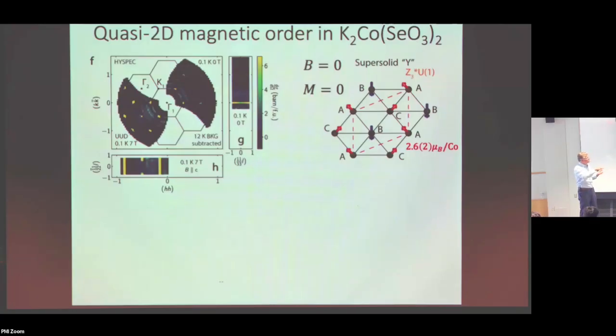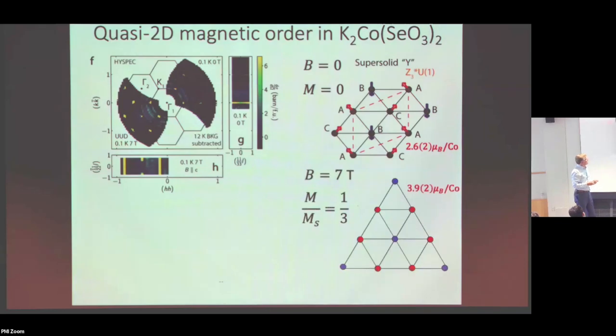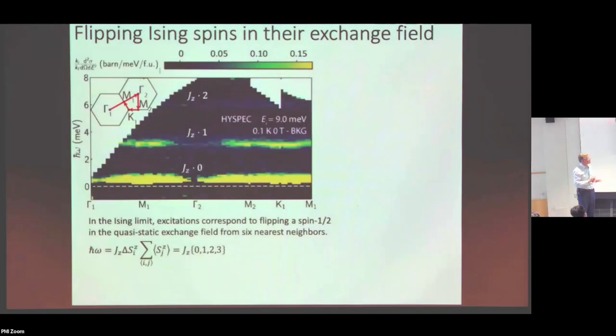But it doesn't imply that the antiferromagnetic ordering is correlated between planes. Those are still uncorrelated. So that is a test of the extremely two-dimensional nature of the system. Even at 0.1 Kelvin, it still is uncorrelated between the planes. Okay, all right. So that actually allows me to draw this kind of structure at 7 Tesla. There we get up to 3.9 μB per cobalt. And basically I have like minority and majority spins. Each blue spin is surrounded by 6 up spins. And then each red spin, I think, is surrounded by as many up as down spins. So that's the nature of the plateau phase, very stable.